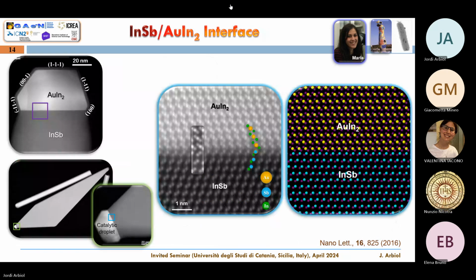So what we do is analyzing the catalyst seed, that is the one promoting the growth. And after the growth, of course, everything is crystalline because you cool down the material and then it gets crystalline. The crystallinity is so perfect that the gold and indium or gold indium composite that you have here, it's perfectly attached to the indium antimonide. You can see here a perfect epitaxy. You can see all the atoms there, the gold atoms surrounded by 2 atoms of indium. This is perfect, but this is happening when you cool down the material. But during the growth, all this is completely liquid. So the droplet, the gold, is completely liquid during the growth.